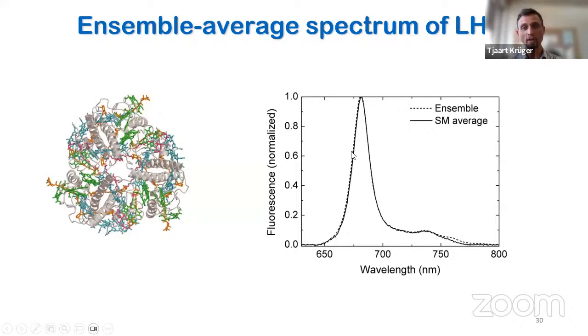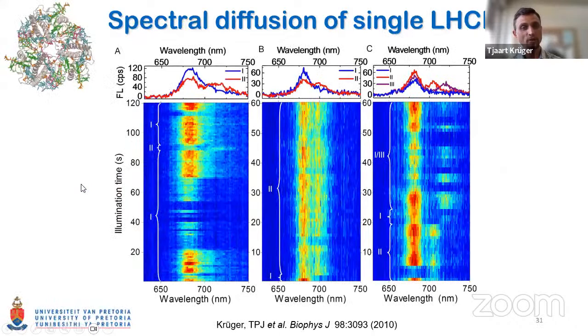Okay, so the ensemble or equilibrium spectrum peaks at around 680 nanometers. Now, if you look at these complexes one at a time, they switch between various different spectral states. So most of the time they would reside in a state characterized by this blue spectrum, in all these three examples, and occasionally they will then switch to a state with enhanced red absorption. So they will exhibit this red band, and sometimes there can be different red bands that can be switched on and off at different times.